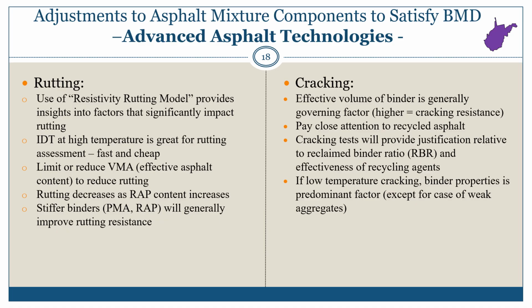One of the other things that Ray mentioned that could be of help is looking at something like a regression model that's been used to calibrate a lot of data to a particular performance test or even field rutting. The resistivity rutting model, which is something that both Ray and Don Christensen from AAT developed, can provide some insights into factors that significantly impact rutting. And one can utilize this very quickly, and I'll show you this in a second.